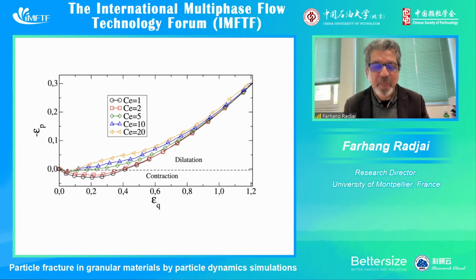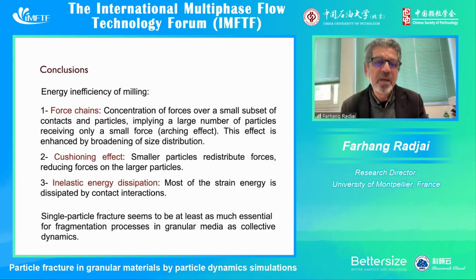Let me just conclude with this slide, because I started by telling you that this process of particle fragmentation is a complex process because it's a multi-scale process. I want to relate this to the inefficiency of milling, in the sense that the energy cost of the milling process is very high. So there are three reasons, basically. First, because we have force chains, and I mentioned it before. So only particles which capture the strong force chains can break.